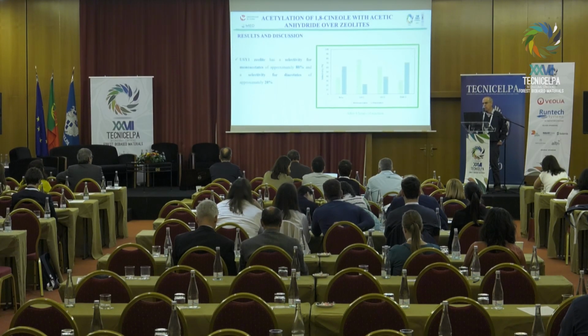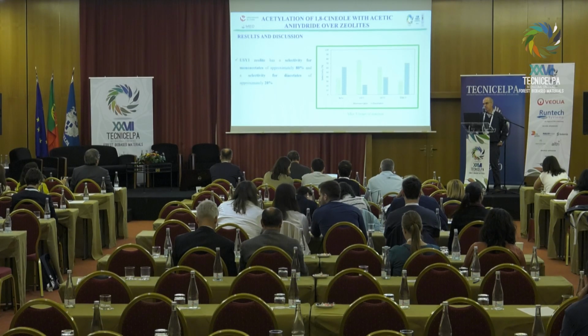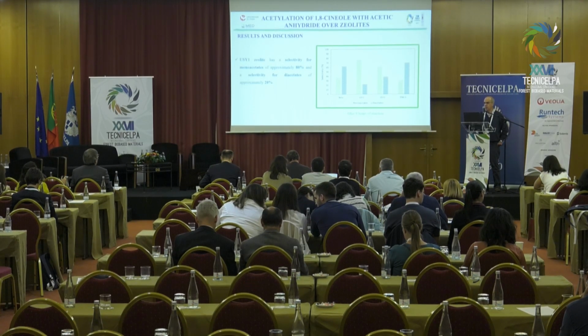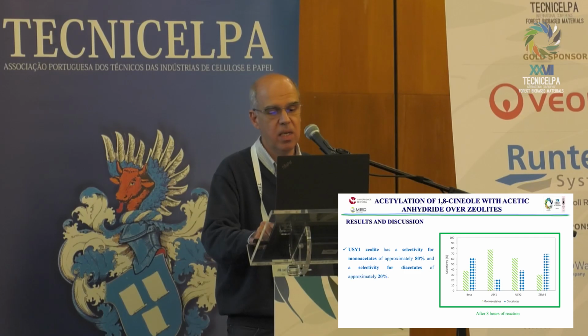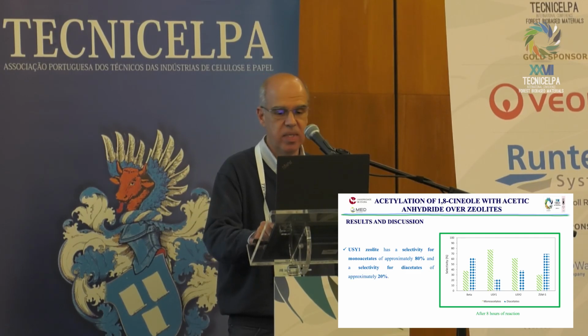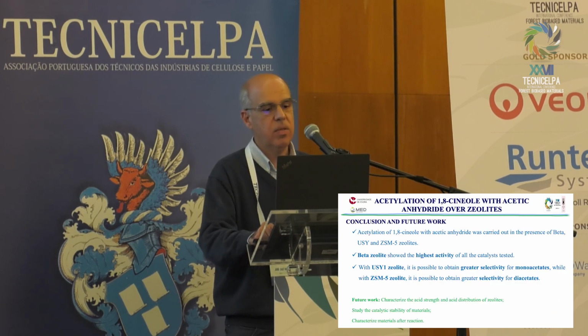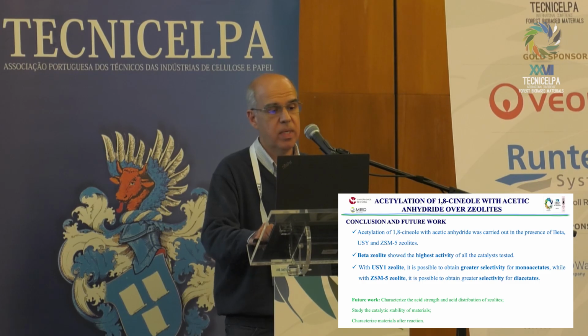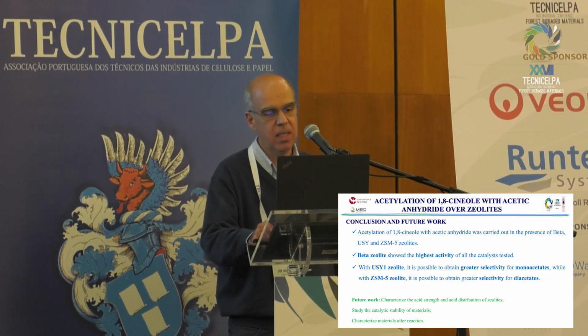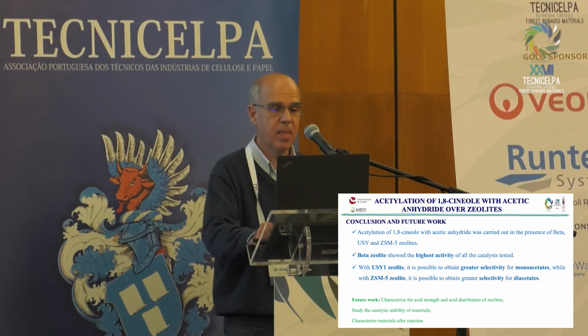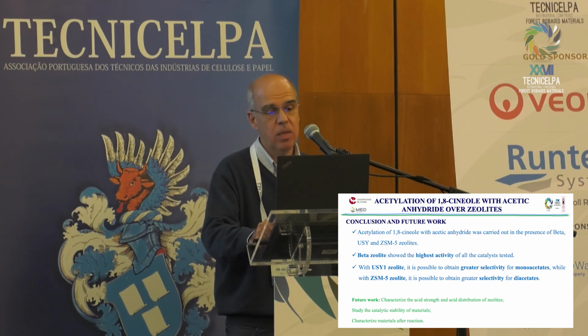The selectivity to monoacetates and diacetates is in the picture. You can see the USY zeolite shows about 80% selectivity to monoacetates and 20% to diacetates. In conclusion, it's possible to carry out the acetylation of cineol with acetic anhydride over zeolites. Beta zeolite showed the highest activity. However, USY zeolite showed greater selectivity to monoacetates.